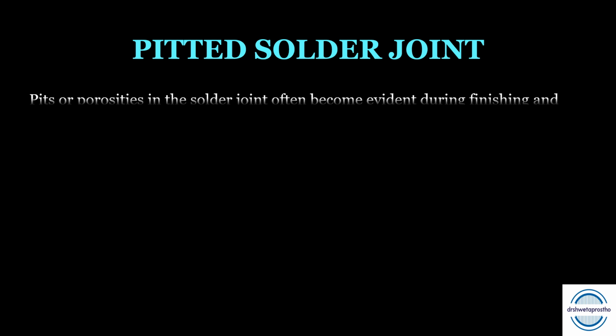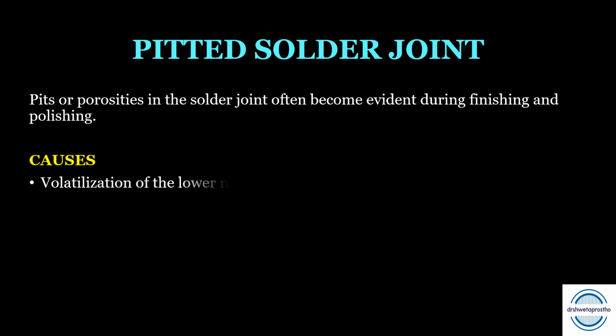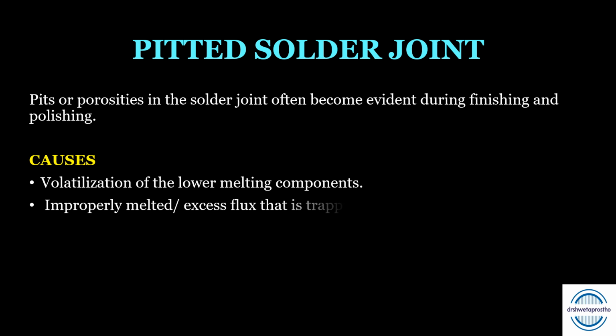Pitted solder joint. The pits or porosities at the solder joint are often seen during finishing and polishing. What are the reasons behind it? First is the volatilization of the lower melting components, and second is improperly melted or excess flux that is trapped in the solder joint.